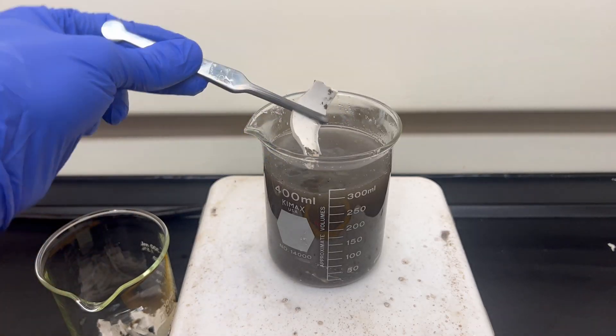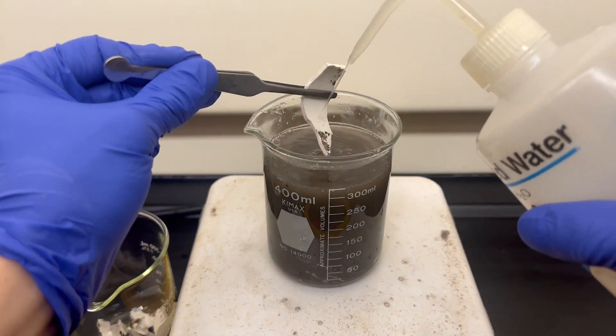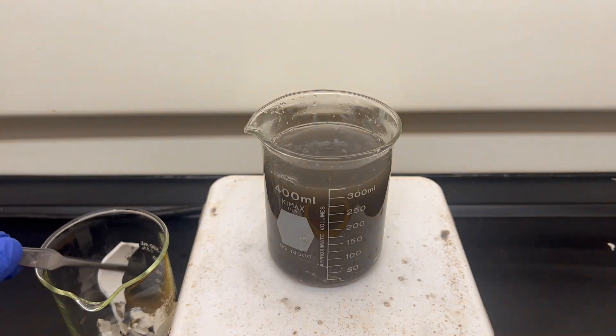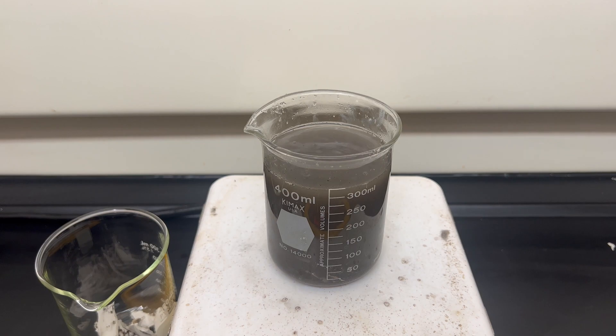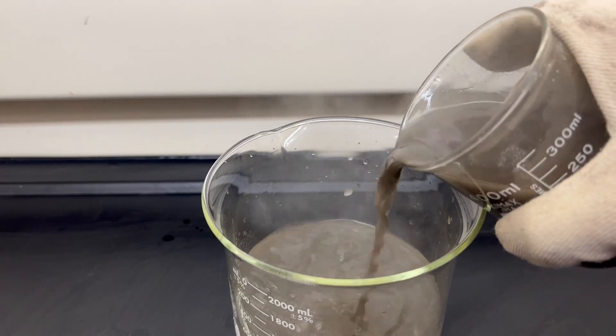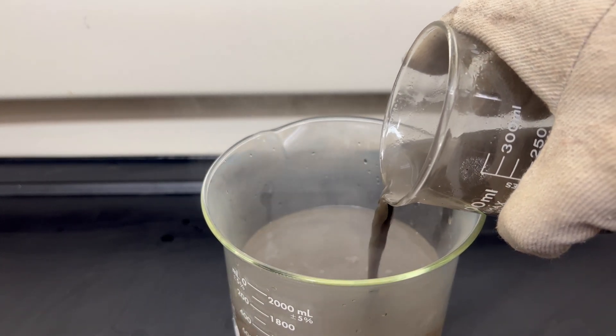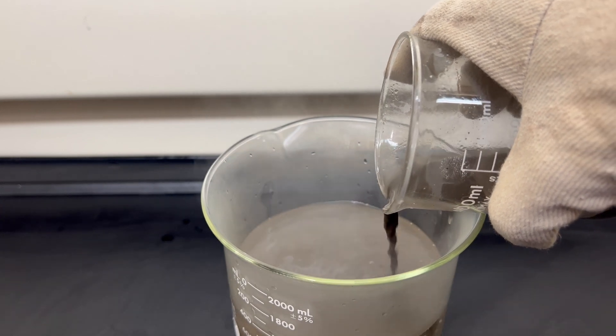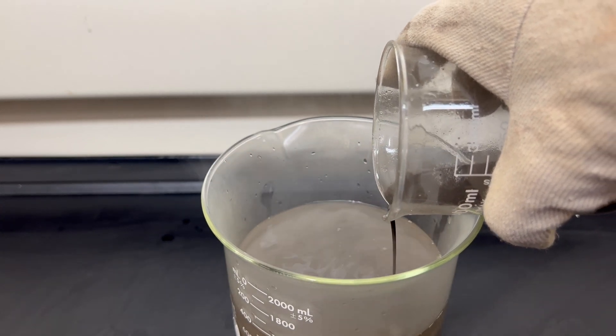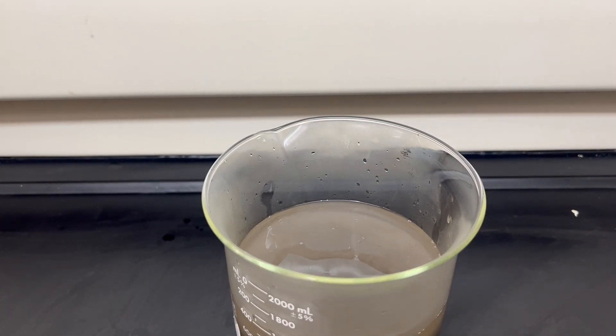I stirred the beaker a few times and over the course of two days, all the soluble acid-reactive products were dissolved. I removed and rinsed the broken crucible shards. Some boron will be lost due to sticking with the ceramic, but most was removed. Tiny shards of ceramic could not be pulled out with forceps, so I needed to employ a trick: by transferring the material to a large beaker with water, we can suspend the fine boron particles while the heavy ceramic sinks to the bottom.